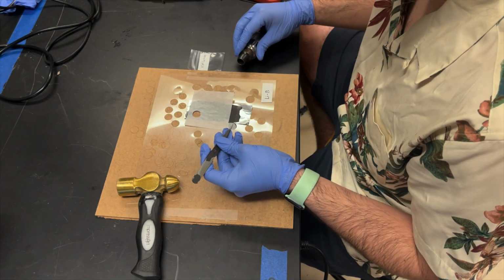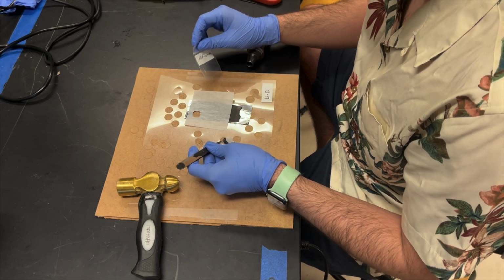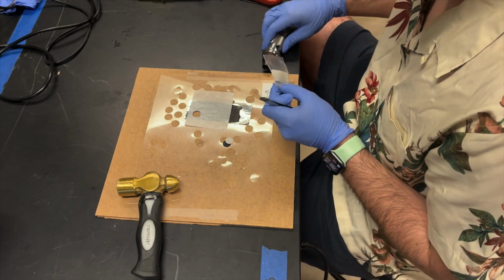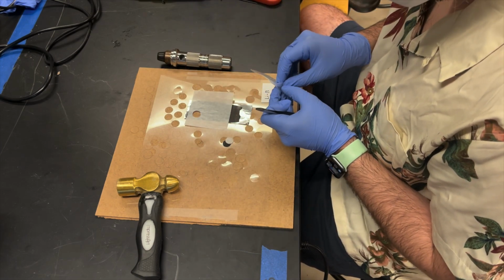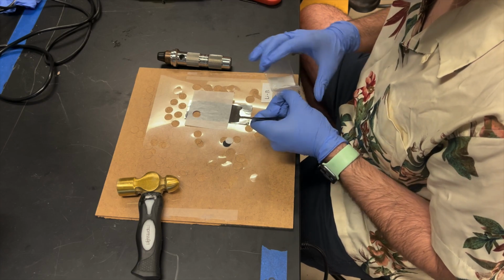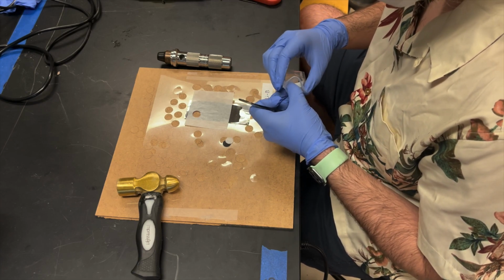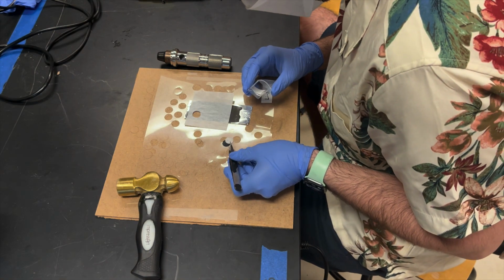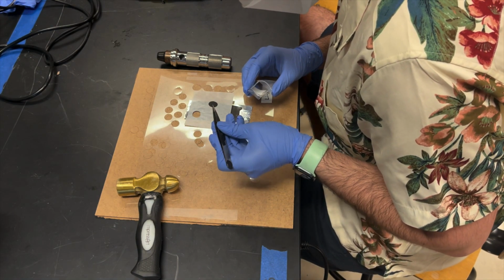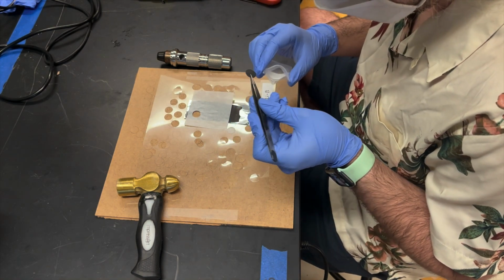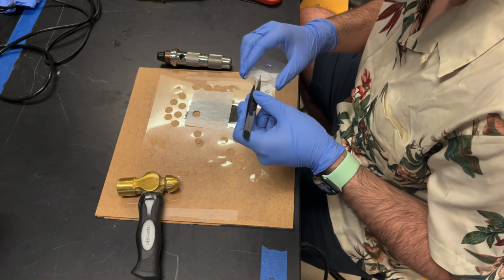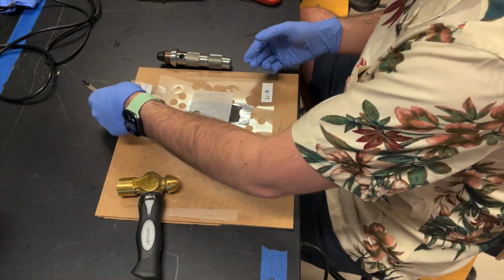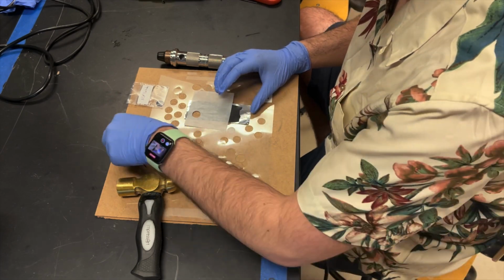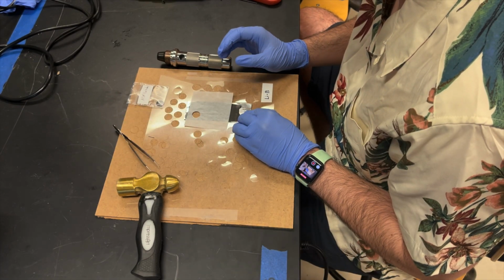It will be important to label these electrodes in the bags that they're contained in and not mix the anodes and cathodes, which may cause them to not work. When done well, a single recipe of slurry consisting of 80 milligrams of active material, 10 milligrams of carbon black, and another 10 milligrams of PVDF can make between 3 and 5 good electrodes.